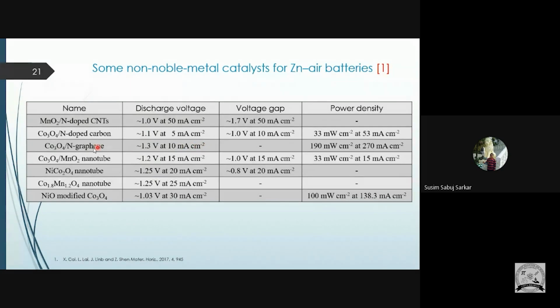Okay, so if we use that MnO2, then maybe the voltage is reduced a bit, but the current is increased. And if you say NiCo2O4 with the carbon nanotube, the voltage also increases somewhat, and also the current is increased. And in the case of cobalt manganese O4 in nanotube, the current is increased much more. And NiO modified Co3O4, it is like 30 milliampere of current. Okay, so these are the data.